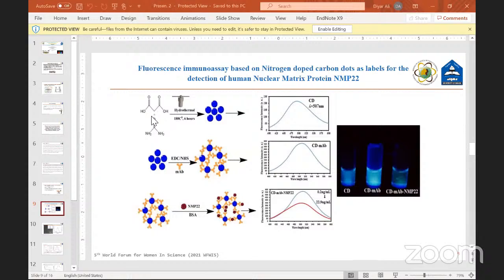As I said, we synthesize the carbon dot by mixing citric acid and urea for 6 hours, and then we get the carbon dot nanoparticle. We measure the fluorescence of our nanoparticle, and you can see it has a fluorescence, but the fluorescence is too low. After that, we conjugate these nanoparticles with antibody by EDC NHS. After conjugation between nanoparticle and antibody, the fluorescence of the carbon dot is enhanced, and we measured the fluorescence.